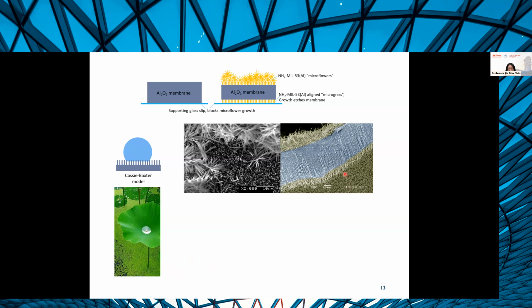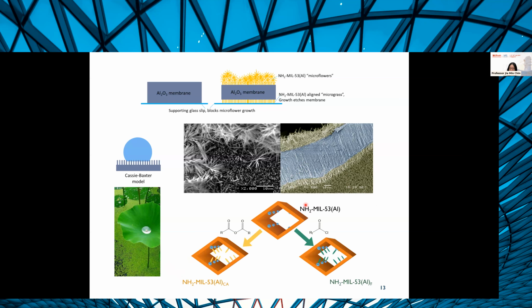In this case, we would have to functionalize these amino MIL53 because it starts off as very hydrophilic. And so we thought, well, amino MIL53 has this handy little amino group here, which we could then react with different reagents and install fluorocarbon groups onto it. So we did that using acyl chlorides with fluorocarbon chains.